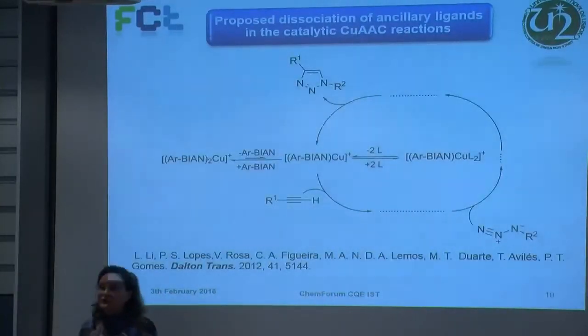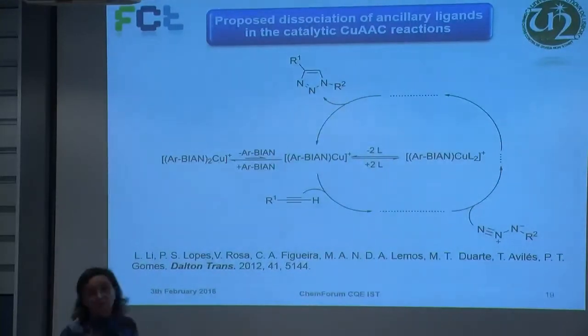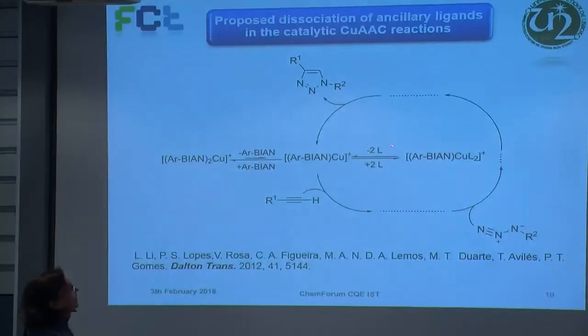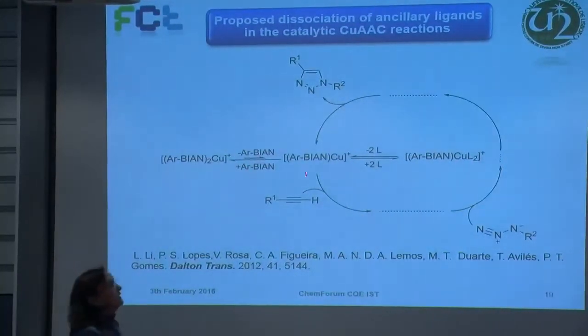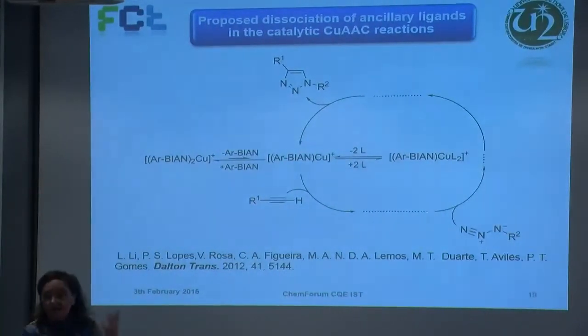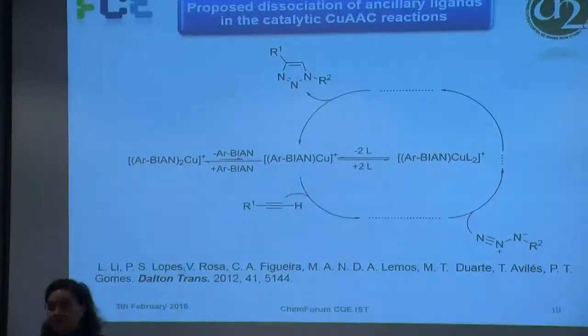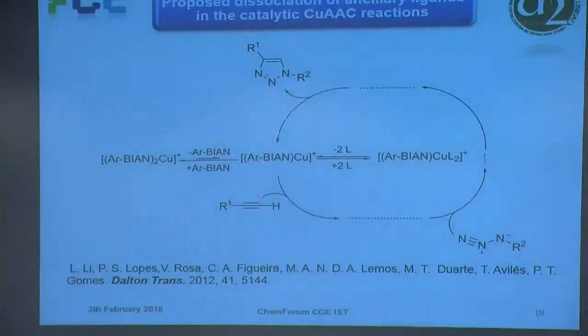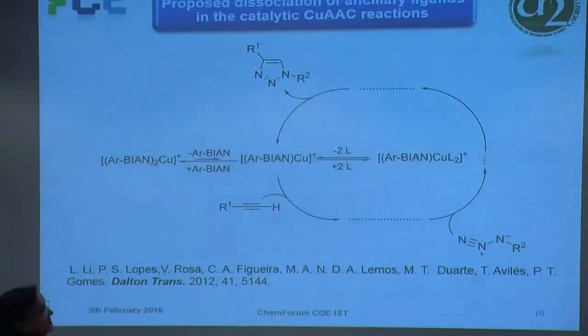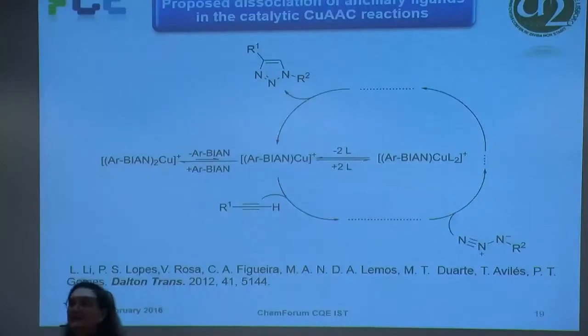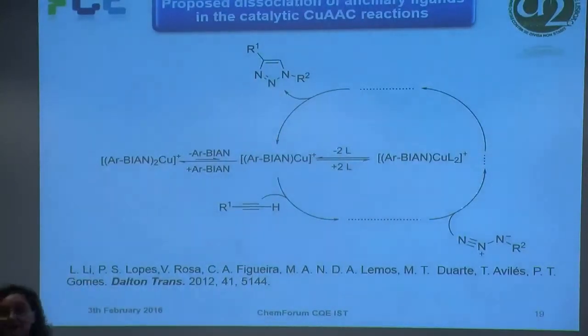Therefore, since the bischelated complexes were worse catalysts and the monochelated were better catalysts, we came to the conclusion that there was an equilibrium in which there was a dissociation of one of the BIAN ligands, and then the dissociated product would be the starting point. We didn't look very much at the mechanism, but it would add the alkyne and the azide and give the triazole. So we thought that the first step would be the dissociation, and that was the reason why the bischelated were worse catalysts than the monochelated.